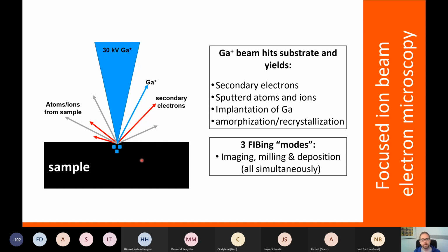which I will discuss in a minute more. But we also have implantation of gallium, which is these three little spots here, which you should keep in mind, that you are actually now implanting a different ion into your material, which may have repercussions later on if you're specifically interested in gallium, for example. And because of this implantation, we also can get amorphization and recrystallization. So we can actually disturb the sample. But in general, we talk about three different modes: imaging, milling, and deposition. And all of this can occur simultaneously.